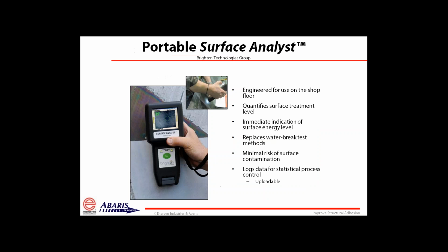So we use an instrument to look at the surface on the shop floor in a general way, so that we can look at a go no-go, if you will, for predicting whether we're going to get wetting on a surface that is compliant with the adhesive that we're using on the substrate that we're bonding to. This particular tool is called the Surface Analyst. It's made by a group called Brighton Technologies. This deposits a very small bead of water on the surface, and then it calculates the actual angle, the contact angle value that you would see. In this illustration, you see 31 degrees. That's a relatively good contact angle.